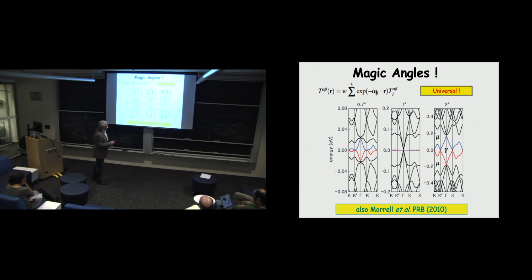Here you can see, if you look at this point in momentum space, two linearly crossing bands, and those are the so-called Dirac bands that we have in individual graphene sheets. And at this nearby, slightly different point in momentum space, we also have linearly crossing bands that are localized, in the limit of weak interlayer tunneling, in the other layer.